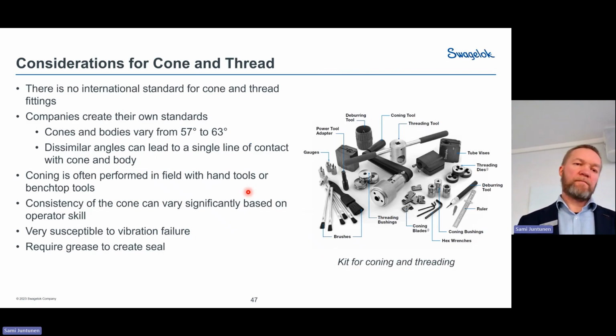But when we do the cone and thread installations, there are no international standards for cone thread fittings. The cones and bodies, the degree of the cone varies from 57 to 63 degrees. If there is any misalignment, then it very easily leaks. When we do the coning, usually in the field with hand tools, so that we can get this fitting leak free, it requires some grease to create the sealing area.